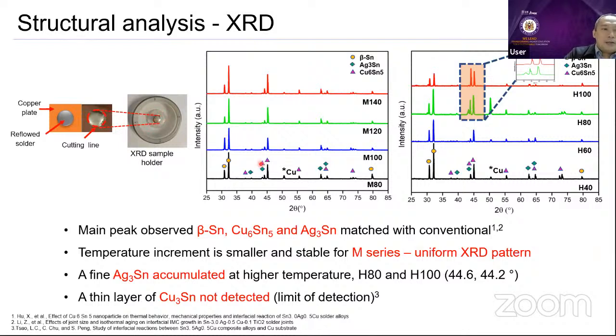Okay, and that's why later on, when we run the XRD, we can get very nice, or we can get to see the important peaks. For example, the important peaks for this one are Cu6Sn5, Ag3Sn, and for sure there is a lot of beta Sn, right? So when we run this one for the medium and then for the high mode, we can get very nice peaks for this IMC. That means that when we have the IMC, then we can have the joint, right?